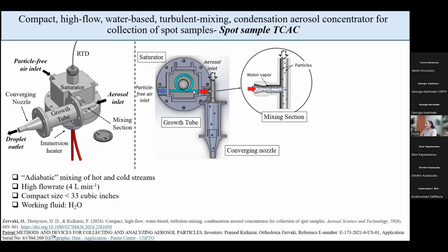Inside the water container, we have a Nafion tube, a membrane that is only permeable to water molecules. At the entrance, we have particle-free air coming in at room temperature, and at the exit, we have a water vapor saturated flow at the same temperature as the water that is being heated inside the container. This water vapor then enters the mixing section, which is a T-shaped mixing section where at the top we have the entrance of the aerosol flow, which is at ambient temperature.